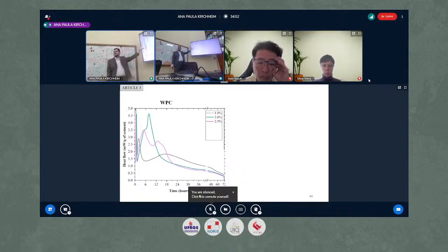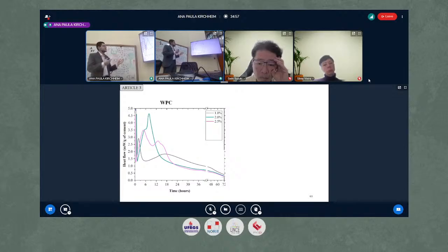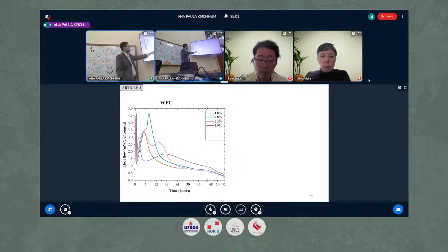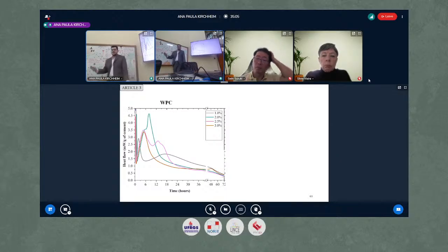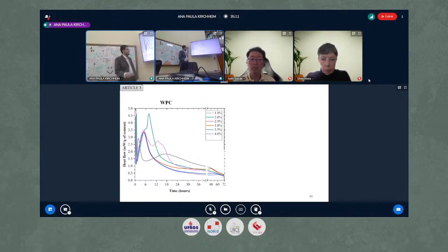So according to the heat flow, the optimum content would be something between 2 and 2.5%. If we add more sulfate, this shoulder peak becomes very late, meaning oversulfated. So we added 3.5, we added 4%, and 4.5%.